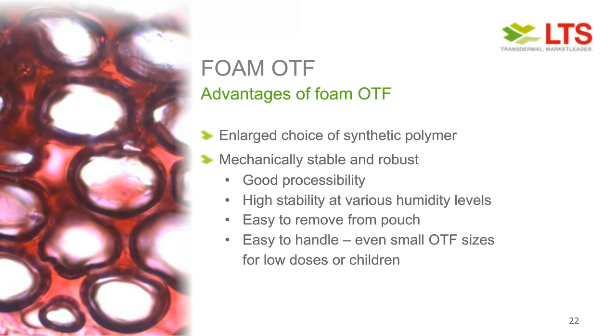The foam wafers are also very stable at different humidity levels. Especially HPMC has a problem. You can either formulate it too dry, so then you have a really brittle product, it's really breaking in your hand, and sometimes patients might not even have the right dose in their hand. Or on the other hand, if the formulation is too soft, patients have significant problems removing the film from the pouch, and this is much improved here with the foam OTF.